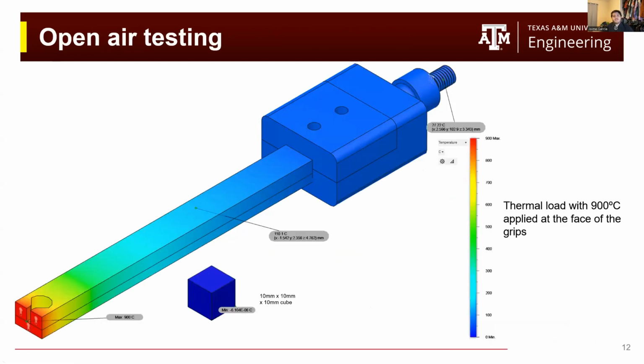We use our understanding of thermal simulations to set up the problem for our load cell. We apply a thermal load of 900 degrees Celsius at the face of the grips and a convective load of 20 watts per meter squared Kelvin on the face of each part to simulate open air. And after running the simulation, we see that the load cell stays cool at around 27 degrees Celsius, so it is safe.